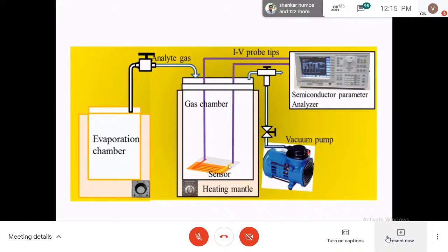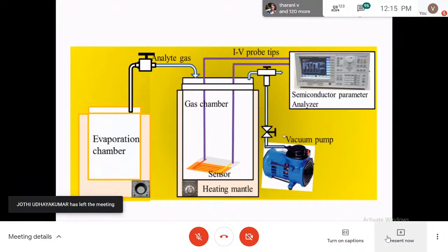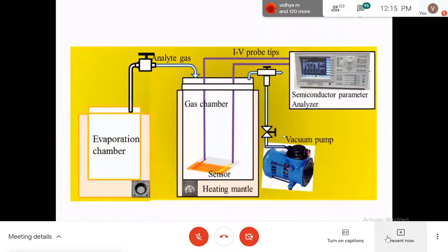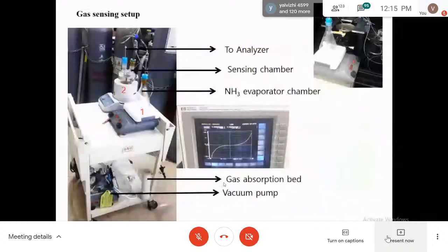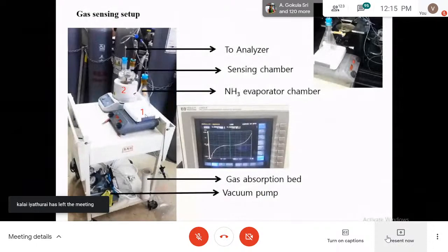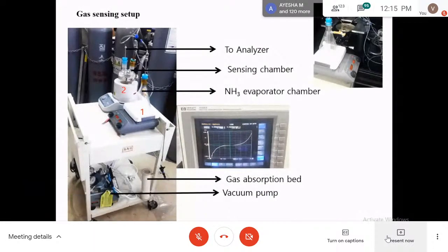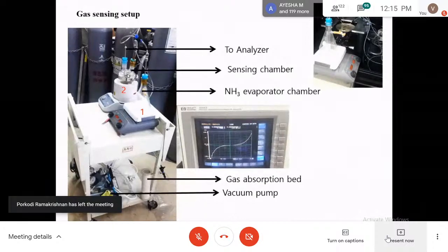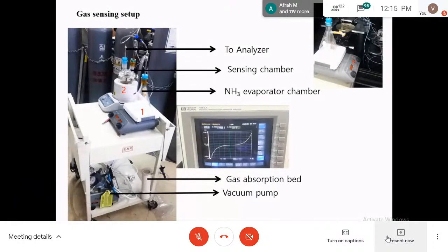and then it will go to the gas chamber here, and interact with the sensor element. This sensor element will give the corresponding electrical response, and that response is measured in the semiconductor parameter analyzer here. For every experiment parameter, we evacuate all the gases using a vacuum pump, and then the test gases were supplied newly. You can see this is a very simple experiment setup. This is the evaporator chamber, and this is the main gas chamber, which contains the sensor element. That element was connected to the IV probe station using copper lead. In the IV probe station, this is the output of the IV using the SPA, semiconductor parameter analyzer.